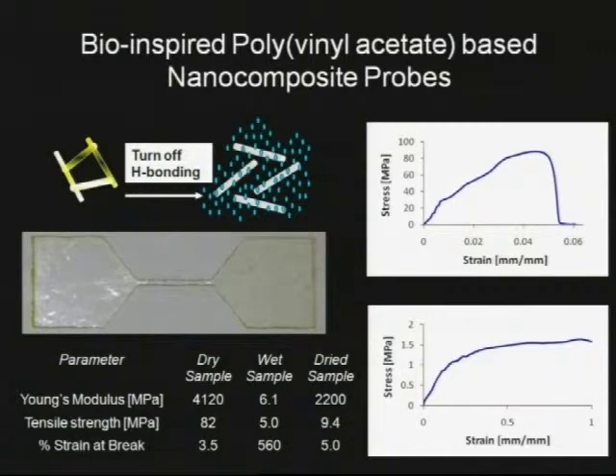We've done some preliminary mechanical properties testing, and we found that indeed the material behaves as advertised. We find that when the samples dry, the Young's modulus, using simple tensile testing techniques, is about 4 gigapascals. When the sample is wetted, it drops down to 6.1 megapascals, and it's reversible, at least to some extent, although this is really preliminary data. Our collaborators say that the mechanism is as such. This polymer is nano-enabled because it incorporates nanofibers that are extracted from the sea cucumber. Those fibers interact in an intertwining matrix when dry, giving stiffness to a relatively soft polymer, which is the base material. It's called PVAc. When it uptakes moisture, hydrogen bonds that are holding the fibers together become weakened. The fibers then don't impart a stiffness onto the matrix polymer, and it becomes soft as the matrix polymer. And we see here tensile testing that verifies that.